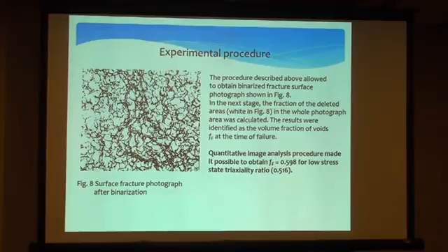The procedure described above made it possible to obtain the value of FF equal to 0.598, which is rather a high value. I would like to remind that the values given in the literature range between 10 and 70%.